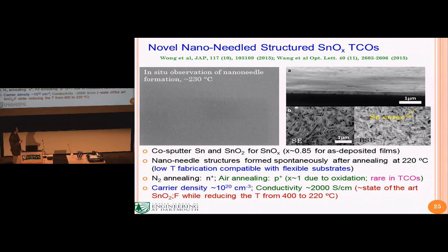So we started to do the experiments. If you want to make a tin-rich tin oxide, you can co-sputter tin and tin oxide targets at the same time. My students, Andrew Wang and Haofeng, were trying this for a while without too much success, until one day they decided they would really crank up the tin composition. All of a sudden, they started to get very interesting structures.